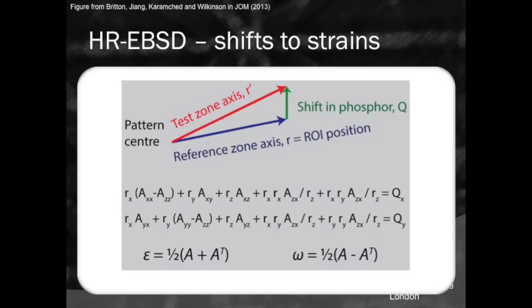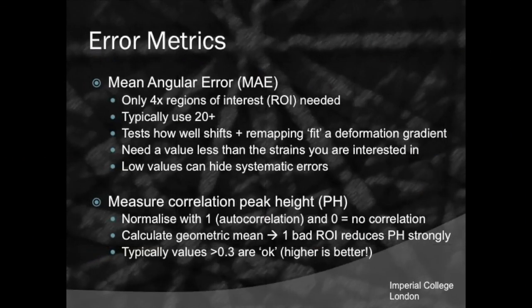I can't extract the hydrostatic strain, so I couple those terms together and sort out the geometry. I effectively extract strain as the symmetric decomposition of the A tensor, and rotation as the anti-symmetric part, within the infinitesimal framework. There are 8 unknown terms for A_ij — 8 strain and rotation components we don't know — and we have 2 measurements for each region of interest. The problem is exactly determined with 4 regions of interest, and adding more gives a best-fit solution whose quality is one of our error metrics.